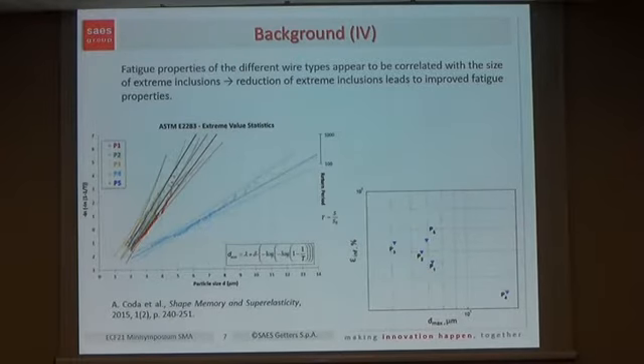E2283, sorry, that are the recommendations for, in general, ball bearing steel, high performance steel, but we apply this procedure also to NiTi. The most important conclusion is that the fatigue limit measured from our strain life curves is perfectly correlated to the maximum inclusion size at a fixed return period. You can select 100, 1,000, whatever you want, but the relation is always the same. There is a perfect relation between the fatigue properties in terms of fatigue limit, but not only, and the extreme inclusions.